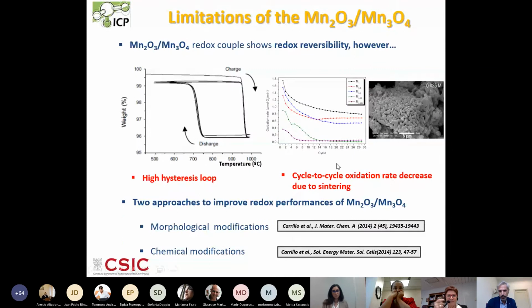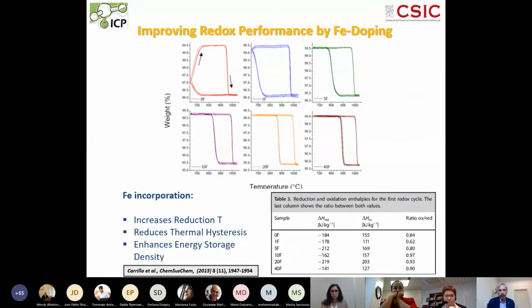Okay, I was speaking about that. So we had two problems: the temperature gap between the charge and discharge, and the low stability, where the rate is decreasing with time of operation. So in order to improve the material's properties, what we did was use iron doping. We tried another doping, but iron is the best. And you can see here that if we increase the amount of iron, we have a narrowing of this gap. It reaches a certain point where we cannot get it better, but at around 20%, we have a quite important reduction. And more importantly, this is done with an increase in the energy we can store in the material. So we have more than a 20% increment in the energy density.